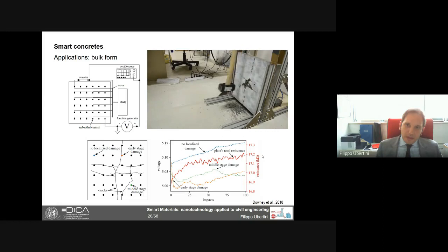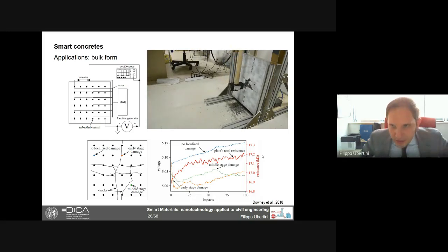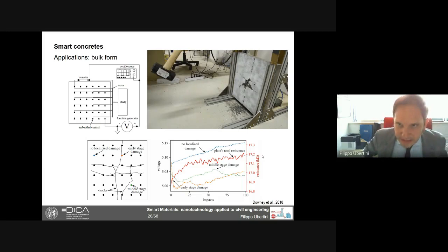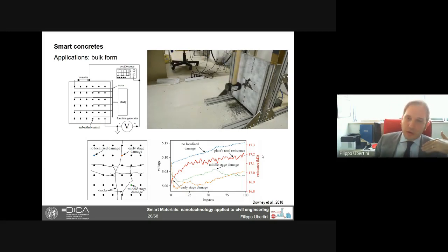The same bulk application is the one we have made to this plate. So this is a bidimensional plate of cement paste with nanotubes that we have subjected to a series of impacts that generated progressive damage. Of course, in the video, the damage was already huge, but at the beginning, the plate was in sound conditions. And then we have a lot of electrodes placed on the other side of the plate, and we measure the voltage drops across all pairs of electrodes.